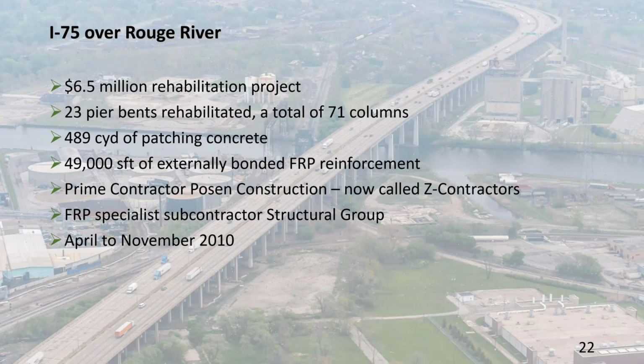The quantities estimated and the quantities that were actually paid for were fairly close, which again, when you work with slag, you have to remember to limit the repair area so you don't wander too far, because that would eventually lead to quite significant increase in your quantities for patching. So overall, the project was well within what we thought it would cost. And initially, we estimated $25 a square foot for the FRP cost, and the low bid came in at $27. So we were quite happy with that.